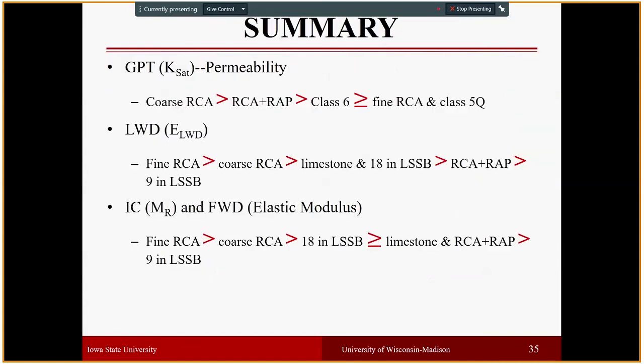So overall summary, of course, as I described, the GPT is the gas permeameter test results, permeability, coarse RCA and RCA materials overall, except fine RCA, showed the higher permeability. And in terms of LWD results, fine RCA and coarse RCA were the highest, provided the highest stiffness than the class 6 limestone material and 18 inches large stone subbases. Then 9-inch large stone subbase test sections provide lower stiffness. And when we come to the APLT, intelligent compaction resilient modulus data, and the FWD elastic modulus data, again the results compared to LWD and between IC and FWD results were consistent. Fine RCA and coarse RCA provided the highest stiffness. Thicker large stone subbases were better in terms of performance compared to RCA rep mix test sections and limestone class 6 and class 5 test sections.